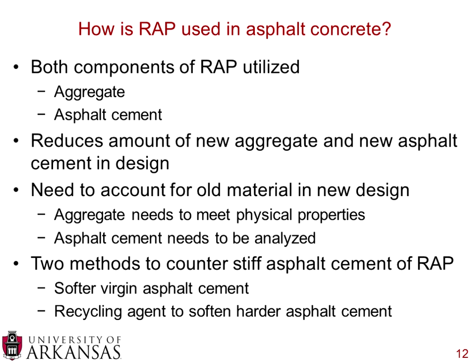So when we're thinking about RAP and how it's used in asphalt concrete, both components of RAP should be utilized, and that includes the aggregate and the asphalt cement. When we do this, we're able to reduce the amount of new or virgin aggregate and asphalt cement in the design. What's very important, however, is that when we're doing our designs, we need to account for this older material, this RAP material, in the new design. So the aggregate needs to meet the physical properties, both the consensus and the source properties. And then also it's important to take the asphalt cement and analyze it to make sure that we understand what we're putting into the mixture.